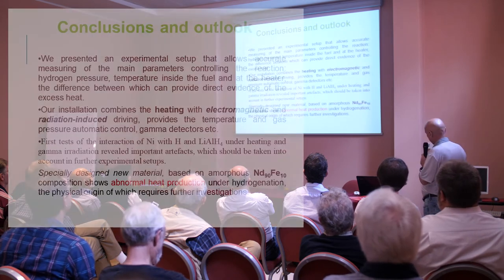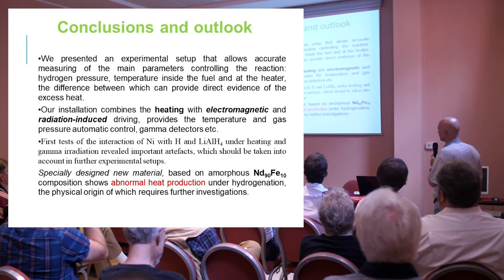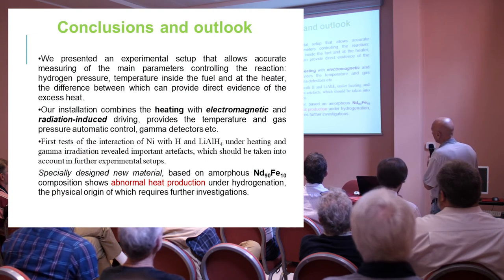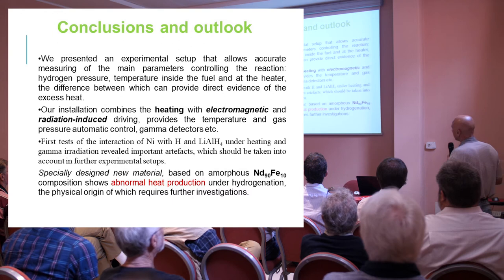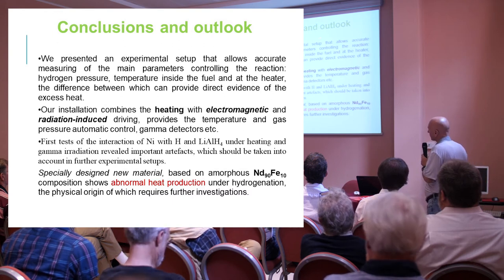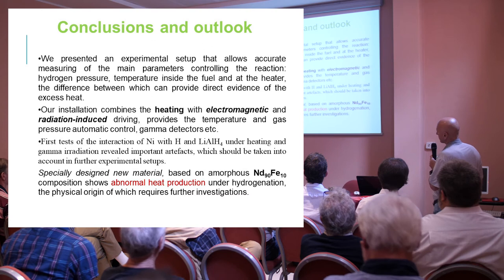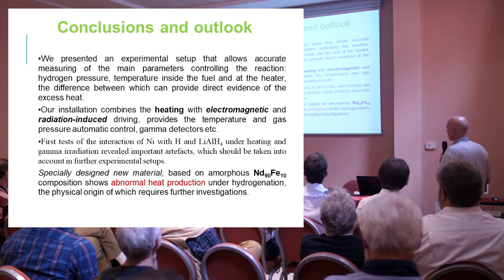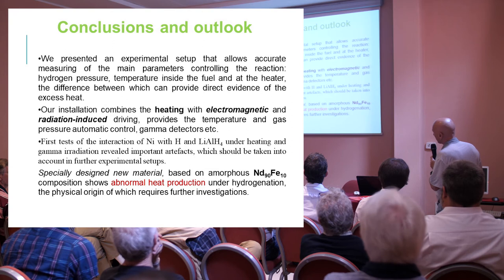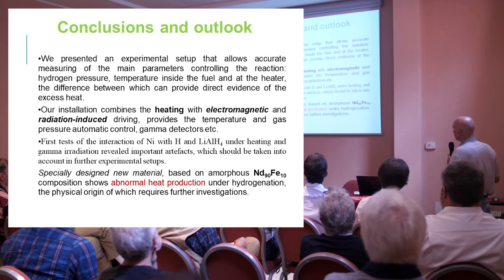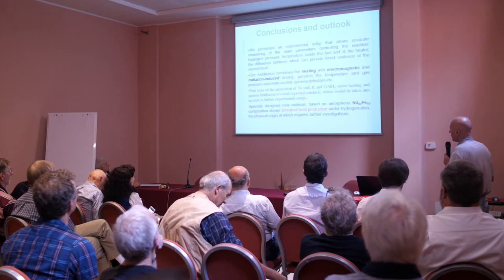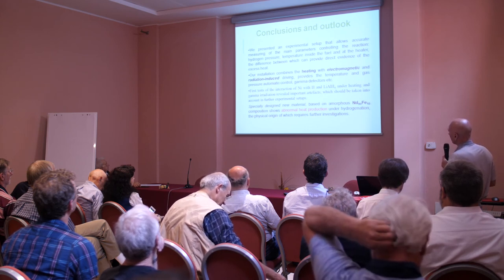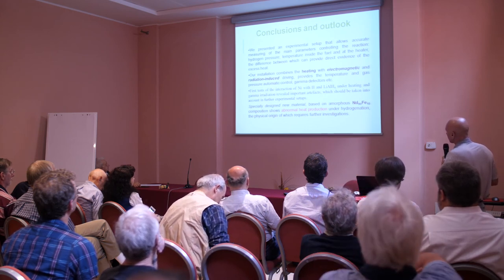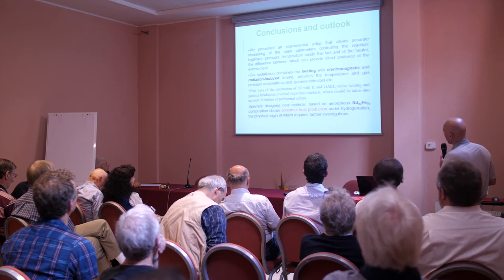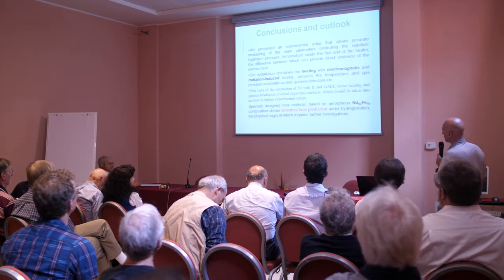Well, so conclusion to this experiment that some heat is produced, and we call it abnormal heat. But whether it has a relation to LENR, we don't know. And the general conclusion is like follows, that we now have this experimental setup that allows accurate measuring of these parameters controlling the reaction. First, pressure, temperature inside fuel, temperature at the heater. The difference can provide some direct evidence of what's going on. Also, we can supply some further driving, both electromagnetic with magnets, etc., and radiation induced.